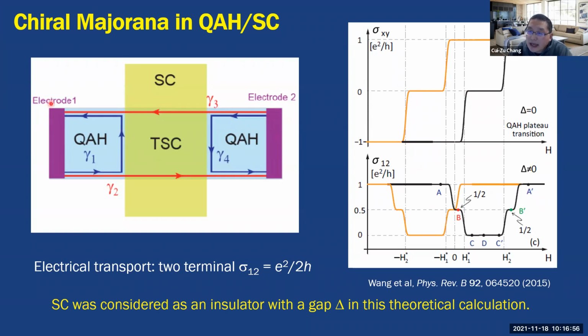You just measure the electrode 1 and the contact 2. You measure the 2-terminal resistance. If you see this kind of transport behavior and this kind of half quantized plateau here, we can see there are 4 half quantized plateaus here. When you sweep the magnetic field, this half quantized plateau indicates the formation of the chiral Majoranas.